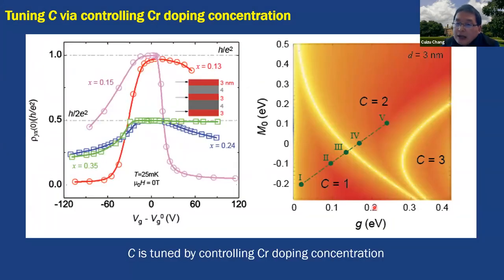The chromium doping Chern number tuning is further demonstrated by gate tuning. We can see that when you tune the gate for the lower doping level, the resistance quantizes at h over e squared. For the high doping level, it quantizes at h over 2e squared. This clearly demonstrates that the chromium doping can tune the Chern numbers in the sample. Our experimental result is also well interpreted by the theoretical calculation performed by my colleague, Taoqing Liu at Penn State.